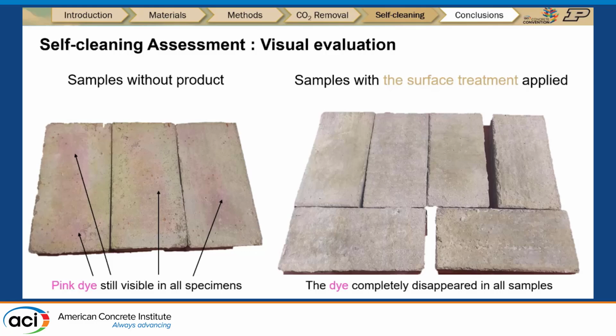Just to give you a visual evaluation: on the left side is a reference group where we didn't apply any titanium dioxide surface treatment. You can see that the pink dye is still remaining after 24 hours. On the right-hand side are samples with our surface treatment, and you can see that the dye is completely removed.